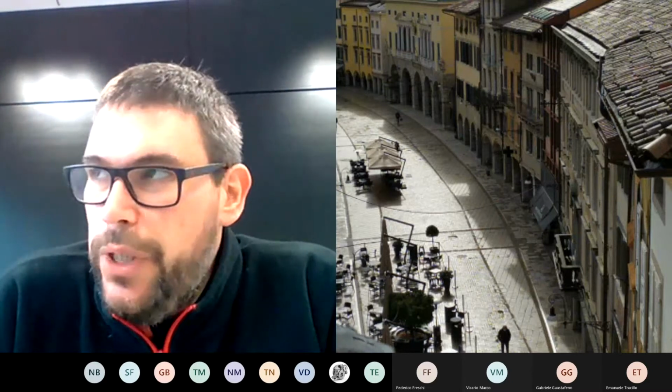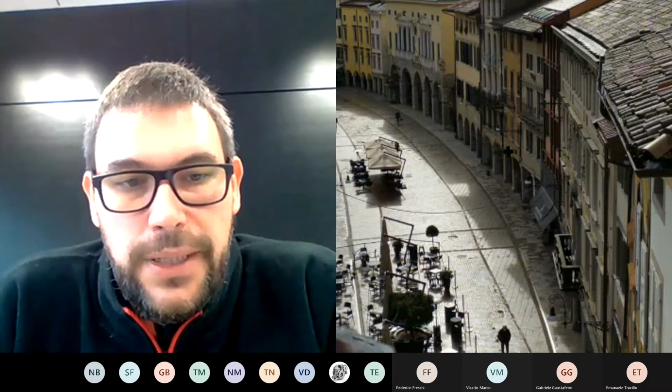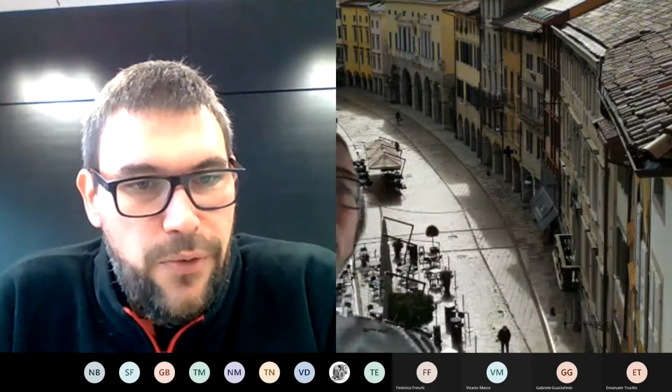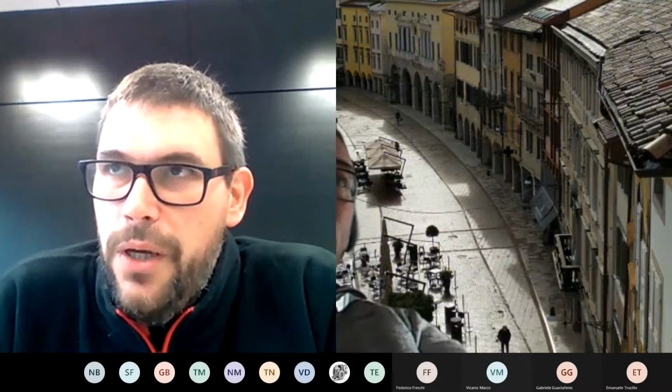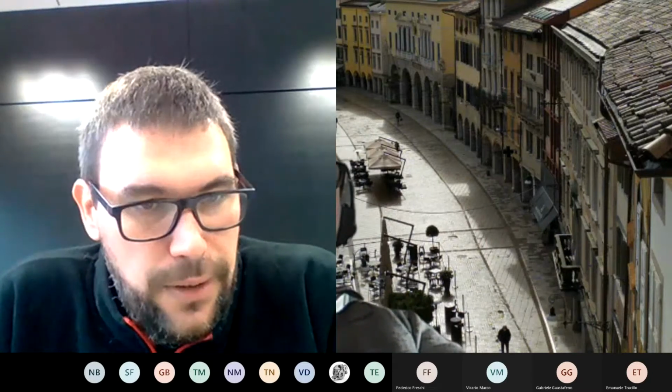And we used a specimen with a calibrated pore that had been done with foundry. So we have a calibrated pore in our samples and we forge it. And after that, we followed it using microtomography.